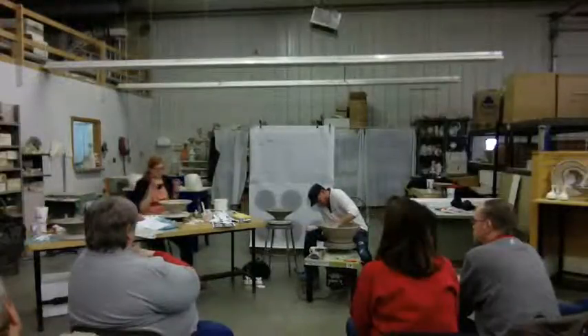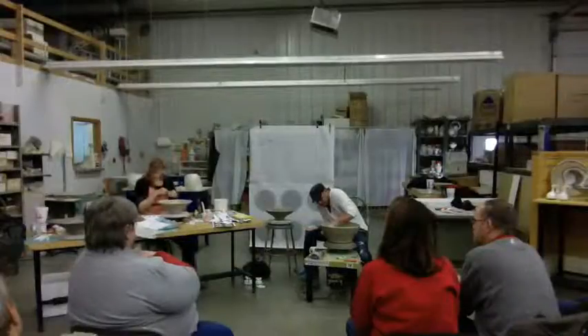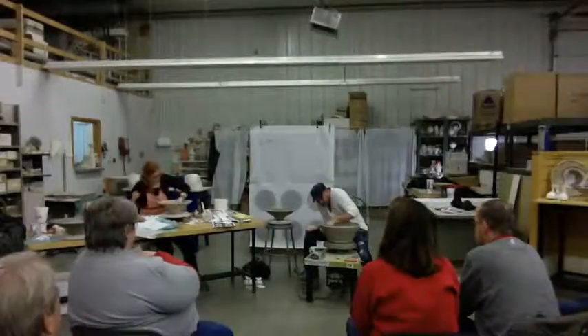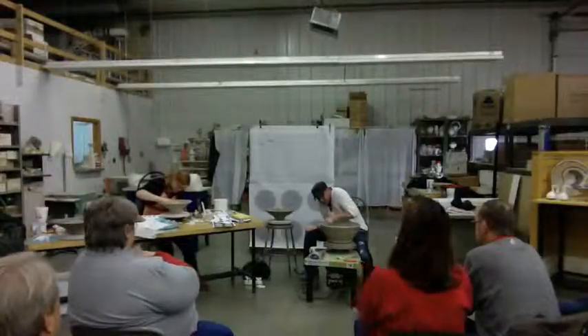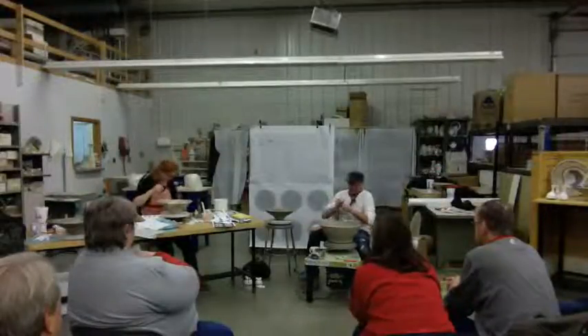Nope. Because it's encased in that underglaze, it creates this little pouch, and there's ash inside the pouch, so you have to chisel it out, and then it's not a clean edge anymore. So it's fairly important for me to get all of them off before the firing. I usually paint over them and then go back and scratch where they're at, so I know where they're located.